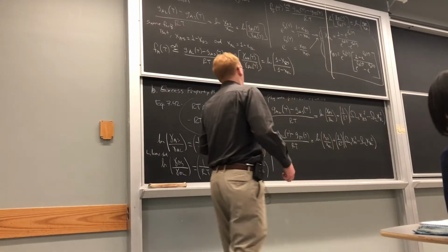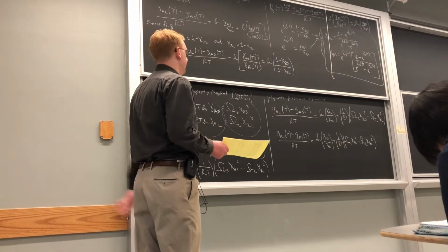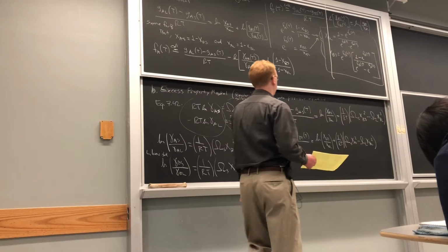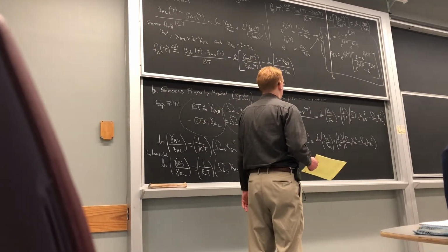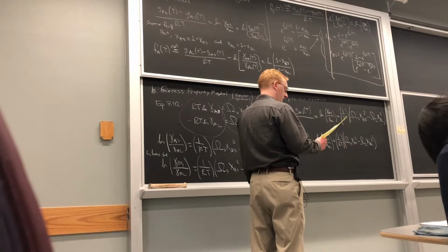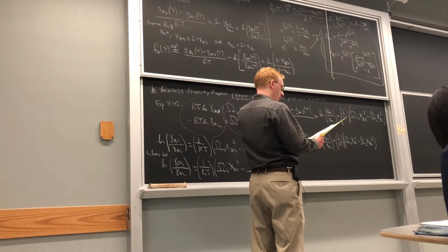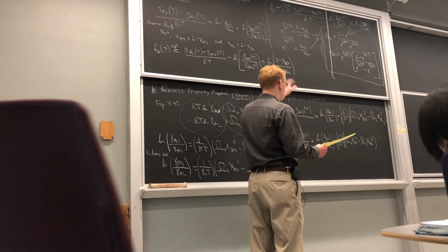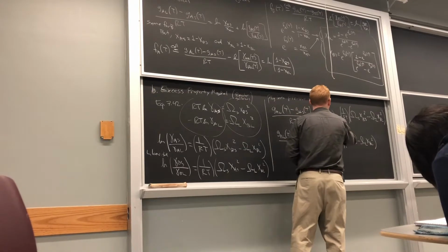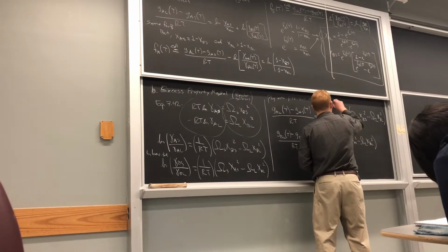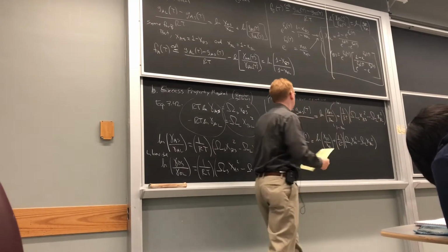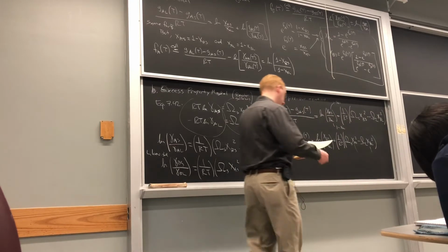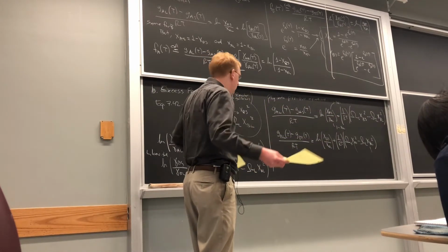Okay. There we go. So, what does this mean? Well, it's a mess. But what it does is it relates, it's two equations, and it relates composition to temperature. It's going to be terribly difficult to solve these for XBS and XBL. Nevertheless, you can solve these equations numerically to give XBS as a function of temperature and XBL as a function of temperature. Again, remembering here that these compositions are going to be 1 minus XBL and 1 minus XBS. So basically we have two equations and two unknowns. Same deal for those A terms. So it's a mess, but you can do it on a computer.